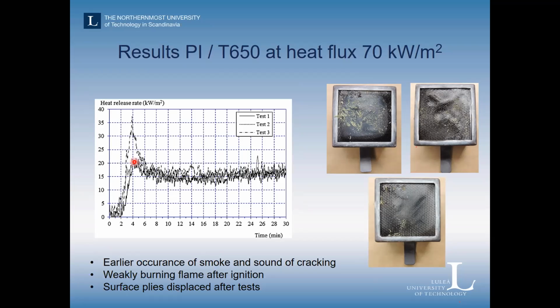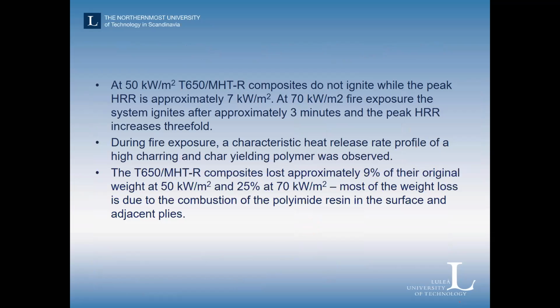There is some weakly burning flame after ignition, but compared to the heat release rates that we observe for polyimide, this is very, very low, and it keeps on burning at a very low rate for over 13 minutes. So it takes a long time.